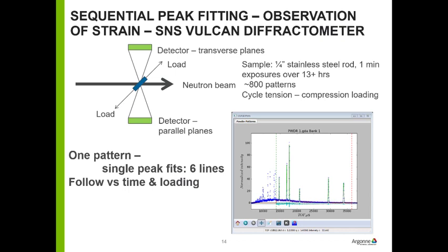What else? Absorption correction should be applied before we index things. Sorry? Like the absorption that we had in the previous presentation. No, all the absorption does is change the intensity. That really won't matter. But anything that shifts the peak positions will matter. What I was going to say before I interrupted myself is to include the weak reflections, but make sure your sample's pure.